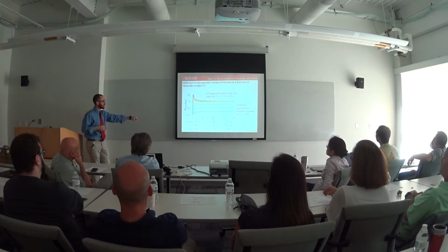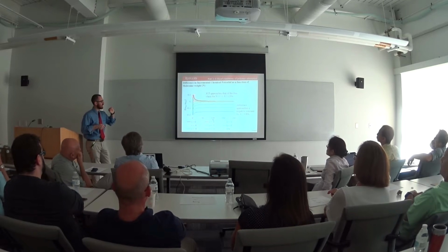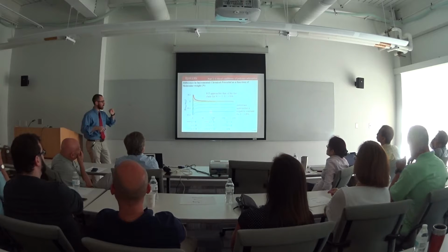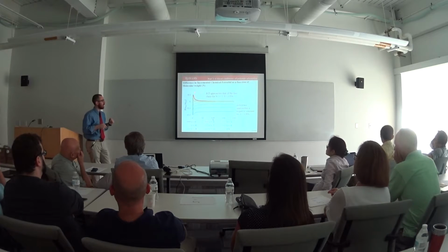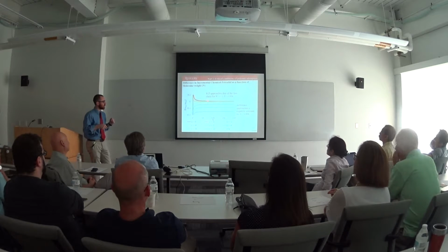So here we have a picture of the difference in incremental chemical potential between an adsorbed and a free chain as a function of chain length. What we can see here is that for different adsorption potentials, which are the different colors, we have different behavior. For all cases where the adsorption potential is less than about 6, we have an incremental chemical potential which eventually becomes equal to that of our free chain.